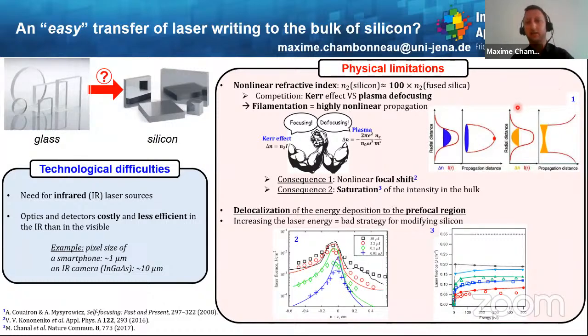So basically, Kerr effect will have the consequence of a self-collapse of the beam, theoretically to a single point. However, when the beam is focused inside the material with a very tight beam size, a plasma will be formed. So you ionize the material, and this ionization results in plasma defocusing phenomenon. So you create a population of free electrons inside the material, and this will defocus the beam. So in the end, you will have those focusing and defocusing dynamics near the focus, the hypothetical focus at least. So this is what we call filamentation, which is a highly nonlinear propagation regime.